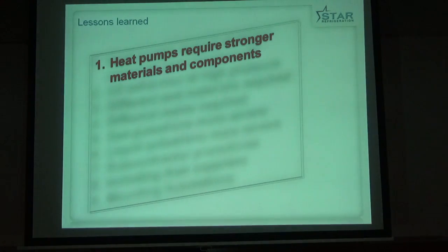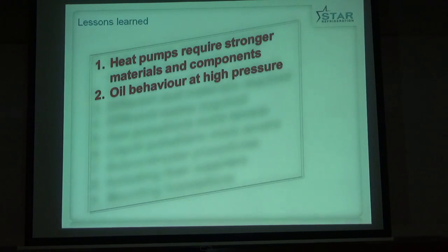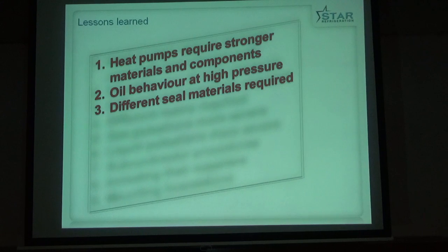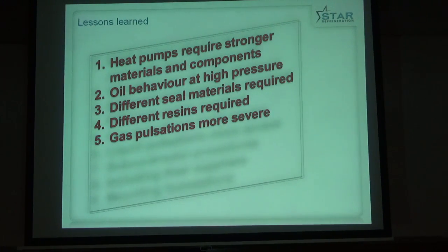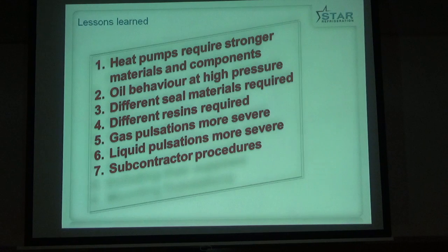So the lessons we learned: we need stronger materials and components. The oil doesn't behave the same way at high pressure. We need different seal materials, different resins in the oil separator. The gas pulsations are much more severe than they would be. Liquid pulsations also more severe. The reason we had the tube failure is because our subcontractor who manufactured the heat exchanger had not followed a robust enough quality procedure, so he had used this dubious material.